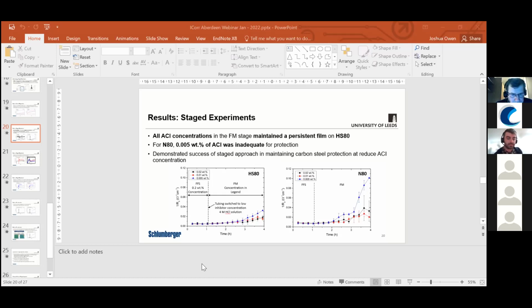So yeah, we've validated the electrochemical measurements with mass loss experiments in the past as well, which have shown so much mass loss that it would be equivalent to around the order of 1,000 millimeters per year. So yeah, it is a pretty extreme corrosion rate that you get in an uninhibited system. Evgeny, is for the higher temperatures, I think some acid corrosion inhibitors don't function as well, I guess, do they?